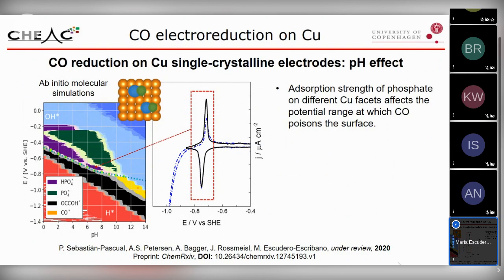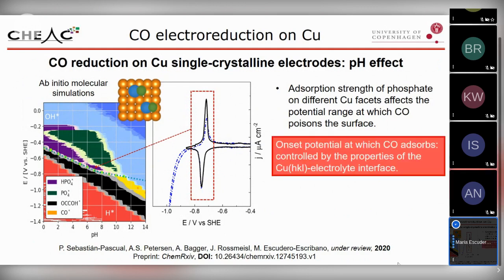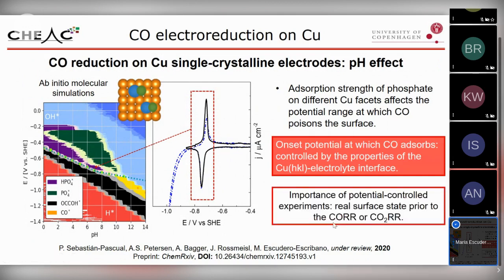And what we can conclude from both experimental and theoretical research is that the strength of phosphate anions on both copper 111 and copper 100 affects the potential range at which CO poisons the surface, and the onset potentials at which CO adsorbs are controlled by the properties of the interface. So this highlights the fact that it is very important to do potential control experiments if we really want to understand and have knowledge of the real surface state prior to the reaction that we are investigating.